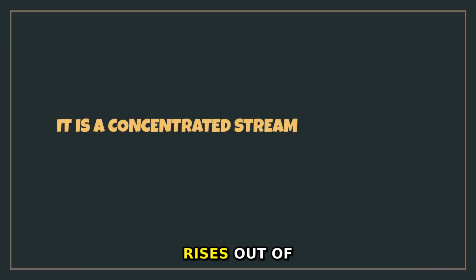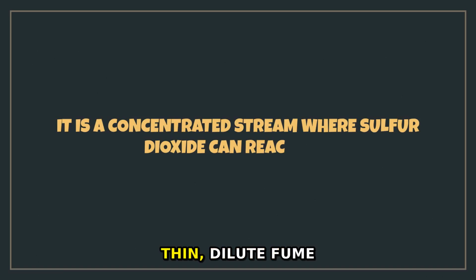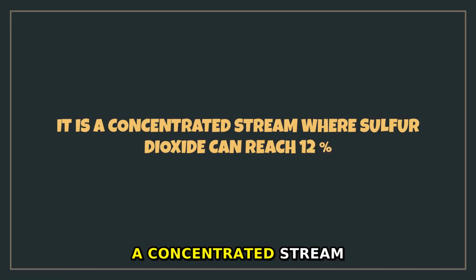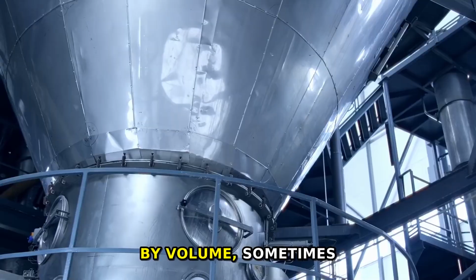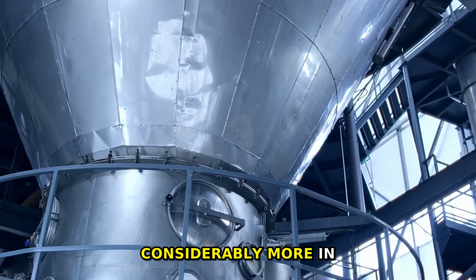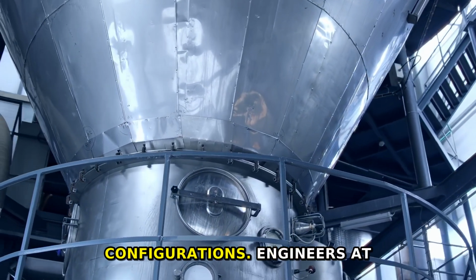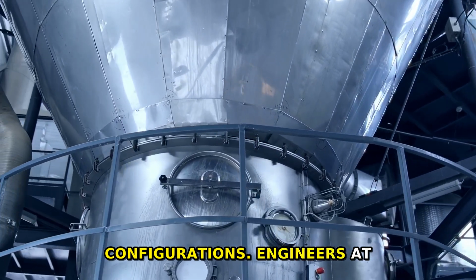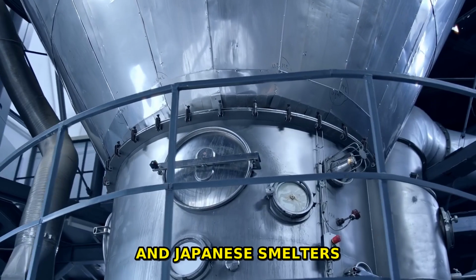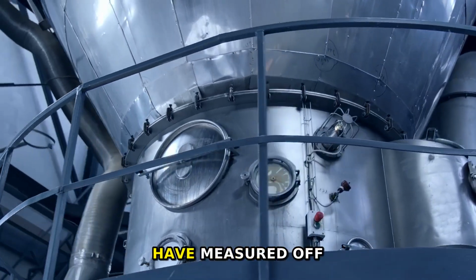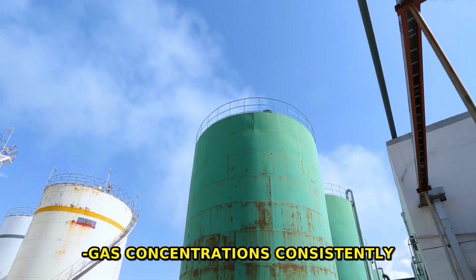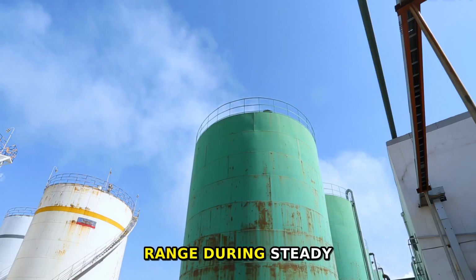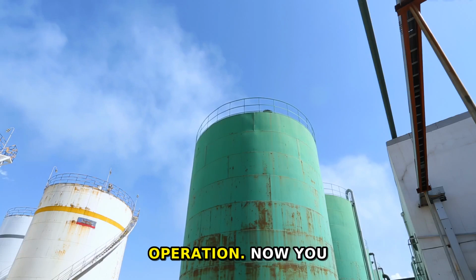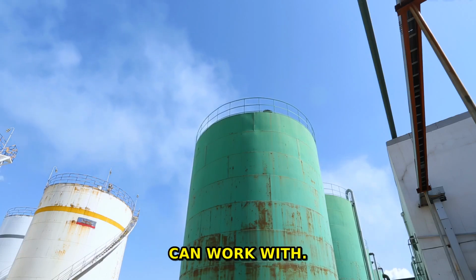And the gas that rises out of the reaction shaft is not the thin, dilute fume of a reverberatory furnace. It is a concentrated stream where sulfur dioxide can reach 12% or higher by volume, sometimes considerably more in optimized oxygen-enriched configurations. Engineers at Finnish and Chilean and Japanese smelters operating this technology have measured off-gas concentrations consistently in the 10 to 15% range during steady operation. Now you have something you can work with.